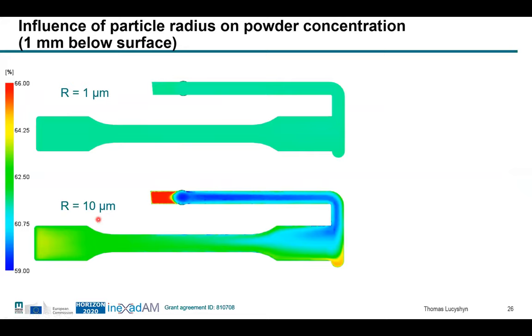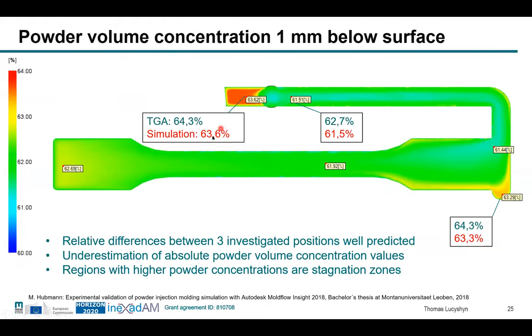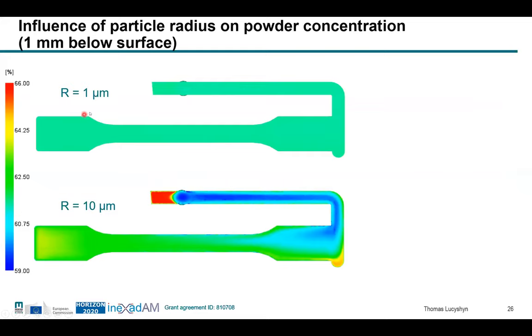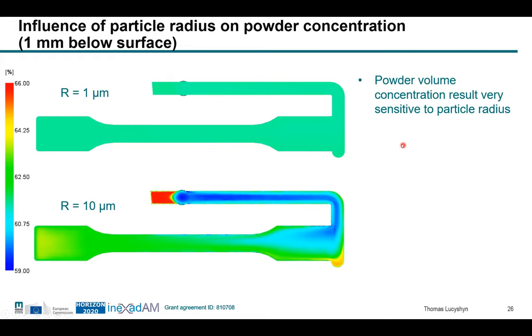So the initial simulations were performed with 5 micrometers and we had this result. And if we do the same with 1 or 10 micrometers, we see that the smaller the particles get, the more homogeneous the concentration is. So we have a very even distribution of the powder. The bigger the particles become, the more inhomogeneous the compound gets. So that's really the bad thing, that the simulation is very sensitive to this particle radius.